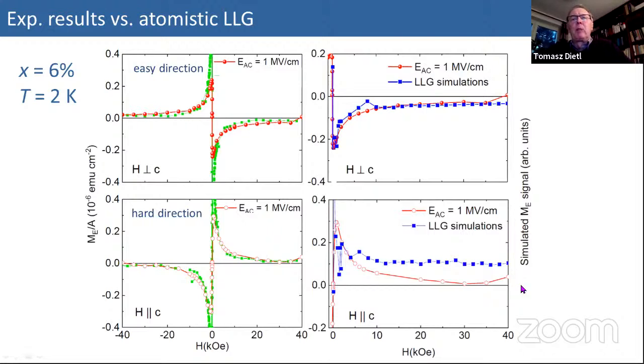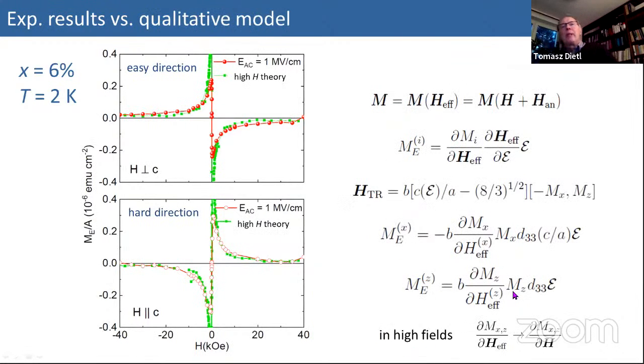And to understand a little bit what physics is behind this simulation, well, it's not difficult to understand. This is the trigonal magnetic field, which comes from trigonal anisotropy as a derivative of the Hamiltonian over magnetization, and contains magnetization along the x-axis, perpendicular to the c-axis, and along the c-axis, and they have different sign. So if you calculate this electric field, using magnetization as a derivative of the effective field, which consists of external field and anisotropy field, you see from these equations that for one direction and for another one, you have different signs. So this can be understood very well.